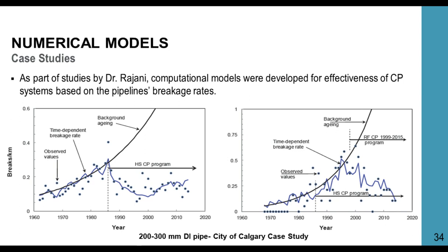The graph on the bottom left shows that hot spotting was applied somewhere between the 1980s and 1990s for this utility. And as you see, you can see the overall rate stabilizes after hot spotting was launched. On the figure on the right, you see that the retrofit was applied in 1999, and there is a decrease in overall break rates for this utility.